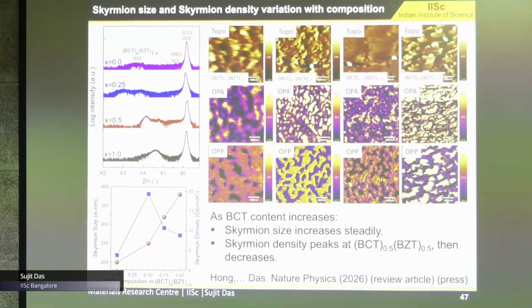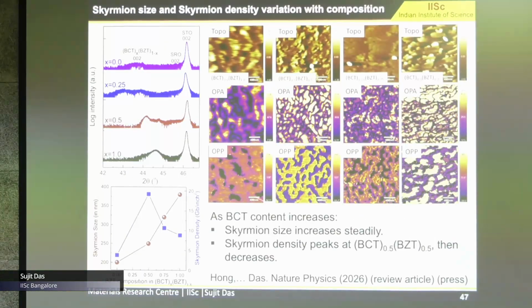So now, can we also make this material in such a way that we can stabilize topological structures? Okay, so we made this material differently. Again, we can see the single crystalline phase, and this is a piezo force microscopy image, out of plane. So this is BCT, this is BZT, and this is the 50-50%. Sorry for the typo.